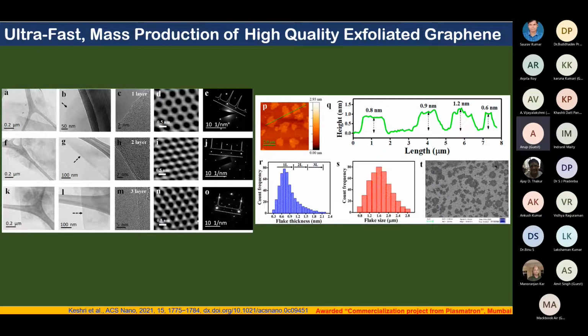But when we take further high resolution images, in C you can see the single layer image. This is a single layer because there are no visible edge lines. After that we did the fast Fourier transform on this, and in image D we get the complete hexagon for the single layer graphene. Image E is the SADP pattern collected from image C, and the intensity plot we made completely matches the single layer.